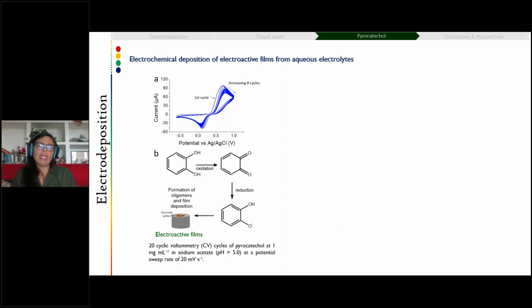So in this case, we were interested in what happens after we cycle the potential of an electrode within an aqueous solution of pyrocatechol, which is the molecule that I have here. This induces an oxidation, a reduction. Professor Vincent Valle from the University of Strasbourg observed that there was a decrease in the current upon cycling.